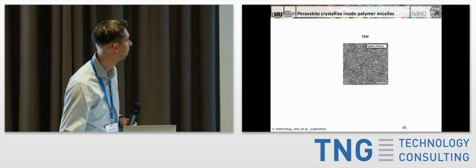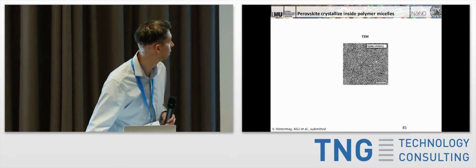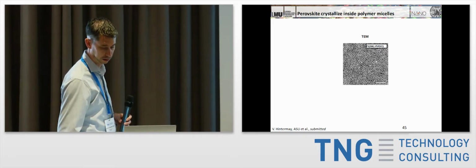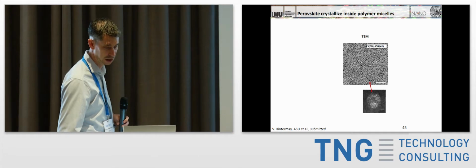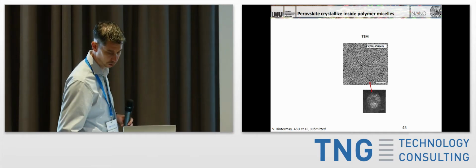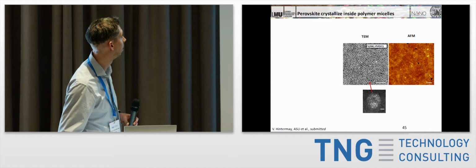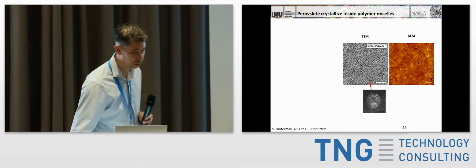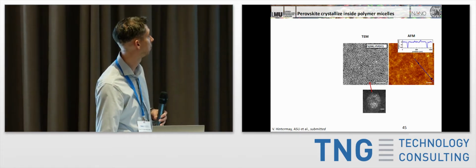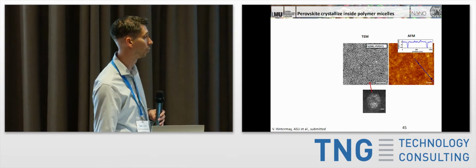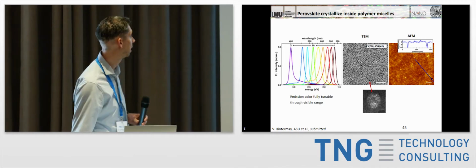So you can see here, this is a TEM image now of a field of these micellar encapsulated perovskite nanocrystals. They're very small. These are on the order of only about 4 nanometers. AFM studies show that they're very, very homogeneous. So we have a surface coverage here in this case of about 99.8%. So you can make very, very nice layers for that.